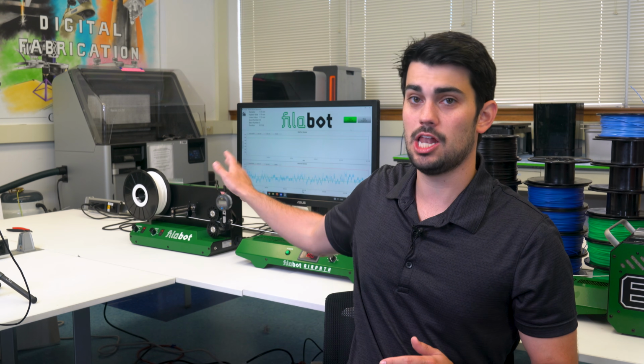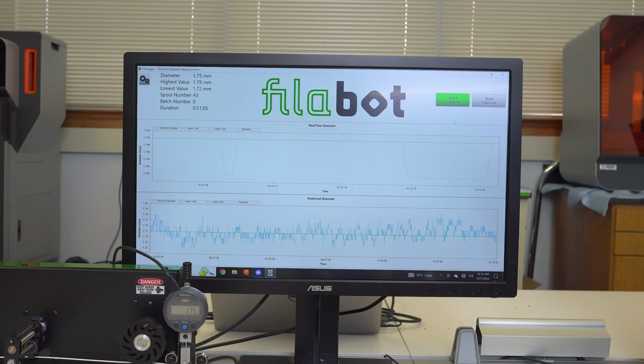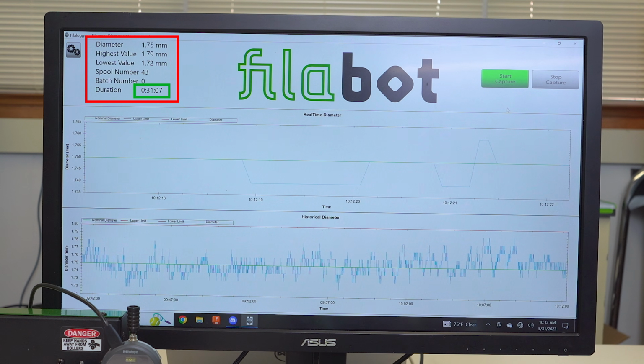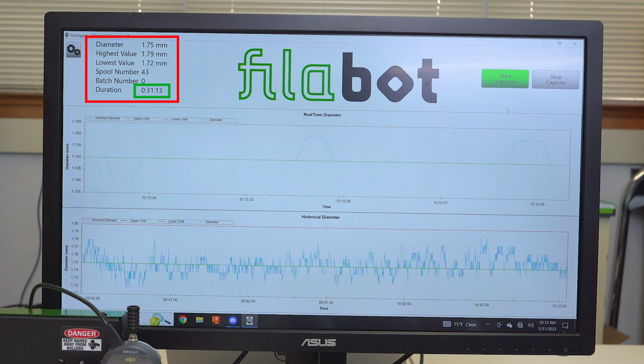I want to quickly show that the last spool was an exception to the norm. I'm working with a white colorant now, which was in spec the entire 330 meters that make up the spool. Also, I was able to shave off 10 minutes from that 40-minute spooling time, so this spool is about done at 31 minutes. This is about the max speed I can achieve with PLA, as I'm limited by cooling capacity at this rate. Next, let's talk about the components and fundamentals of plastic extrusion.